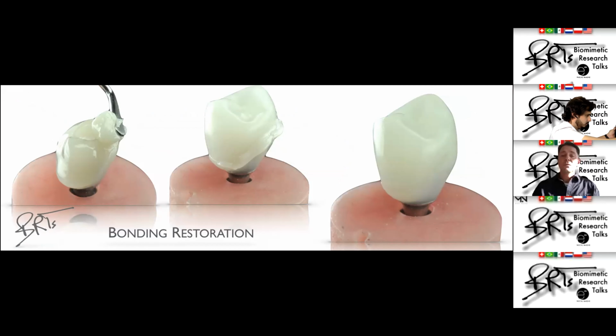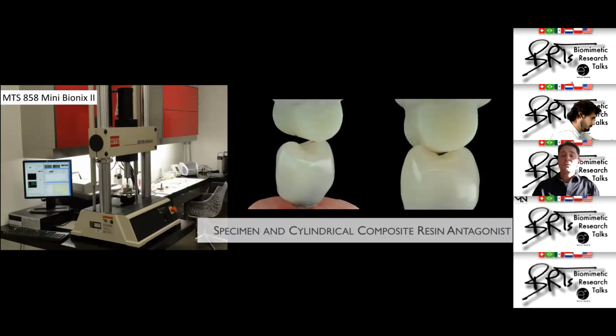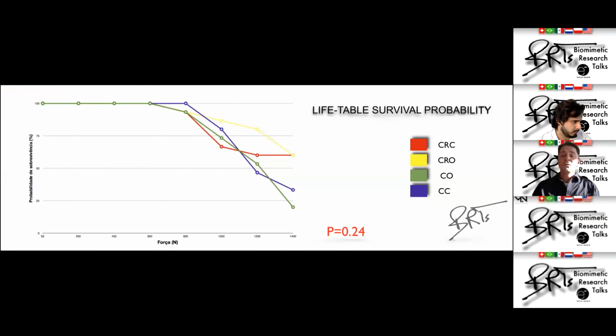So we did the same. We went to the fatigue machine and loaded for 8 to 10 hours. Once we had the test done, as a result, we can see that there was no difference between the groups. But one thing we need to point out is that all samples survived up to 600 newtons, which is the maximum bite force.